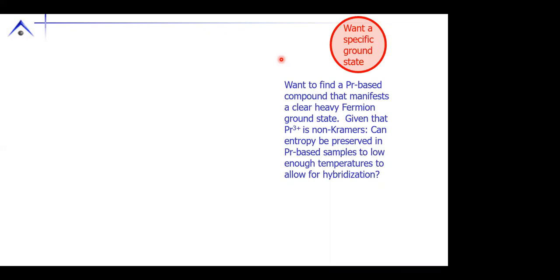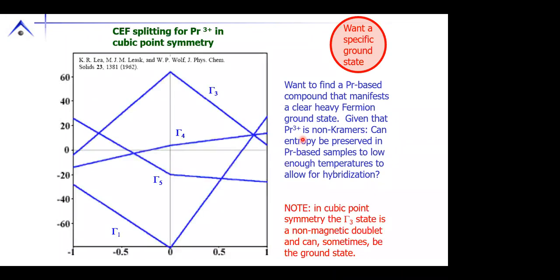On the other hand, praseodymium is non-Kramers. So if you're not careful, it can drop to a singlet ground state, at which point you have no entropy to transfer over to a heavy electron state. So if you're thinking of wanting to have a praseodymium heavy fermion, the first task is to preserve entropy, okay? So if we look at Lea, Leask and Wolf from 1962, where they plot for cubic point symmetry the CF splittings of all the rare earths, we can see that a gamma-3 splitting is a possible ground state for certain situations. The gamma-3 is nice because it's a non-magnetic doublet. Doublet preserving entropy, non-magnetic, it rules out magnetism as a way of removing this entropy.